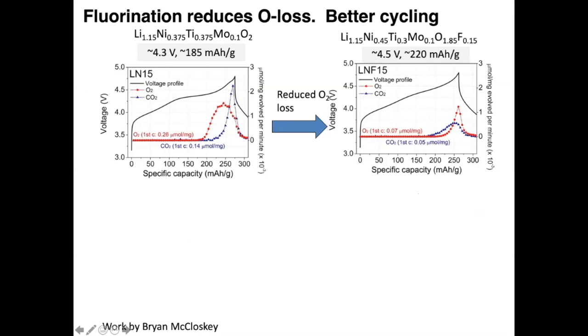And if I compare here, this is done with DEMS with Brian McCloskey. The red curve is the oxygen loss when you charge. This is a DRX oxide, this is a nickel compound. When you charge it to 4.3 volt, you start right away seeing oxygen loss come off. Okay. If you fluorinate that material even lightly, in this case 7.5%, what you see is that the oxygen content is significantly reduced already. And I'm not an expert in this, but according to Brian McCloskey, the oxygen content coming off here is already much lower than what comes off NMC materials.